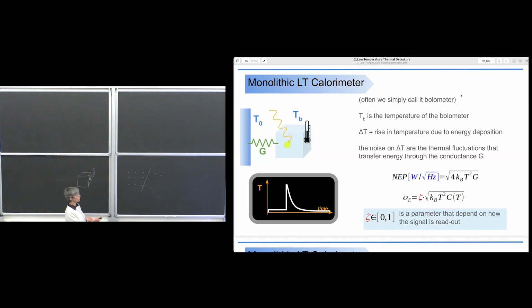And you have temperature fluctuations because you have a thermal conductance here. The system of your absorber is not a fully isolated system, not an adiabatic system, and therefore you have a temperature fluctuation. From the point of view of energy resolution, the temperature fluctuation transforms into this amount of energy. And if you want to use this evaluation of the fluctuation to evaluate the energy resolution achievable with your detector, you have to take into consideration that you have to read out the temperature, and therefore you have to add here a constant, a parameter that depends on the signal readout.